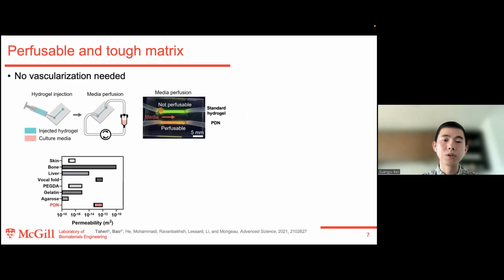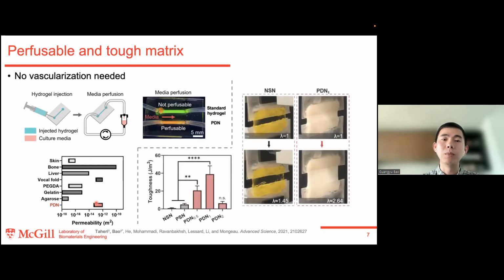And since the pores within are interconnected, the media can be perfused through our hydrogel that has been pre-injected into the microfluidic channels, but the media cannot perfuse through the conventional hydrogel, which is a covalently cross-linked hydrogel. And when we measure the permeability of our gel, it is very similar to some of the tissues, such as the vocal fold and also the bone. And the value is orders of magnitude higher compared to the commonly used standard hydrogels. Meanwhile, the pores did not impede the mechanical toughness, so our hydrogel can be tuned to be even 40 times tougher compared to the covalently cross-linked hydrogels. And from the photo, we can see that our hydrogel is highly stretchable. However, the standard hydrogel ruptures at very small strain.